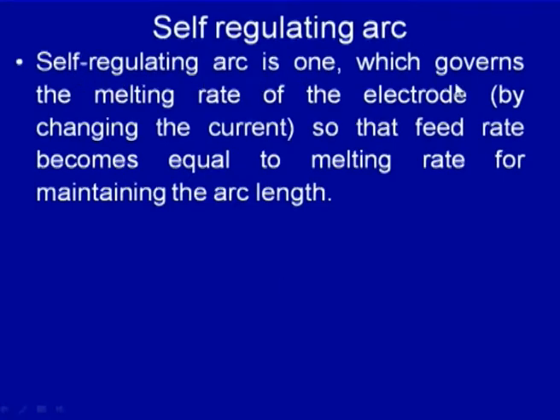So, a self regulating arc is one which governs the melting rate of the electrode by changing the current, so that the feed rate becomes equal to the melting rate for maintaining the arc length. This is one of the important things in this process: in the self regulating arc, the melting rate is controlled in such a way that it is equal to the feed rate, so that when the two are equal, the arc length is maintained.